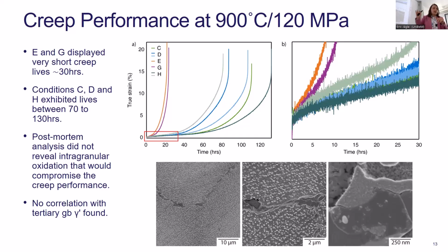So condition C here looks okay, but it doesn't stick out. So the gamma prime distribution didn't seem to influence necessarily the creep performance. So just the finer gamma prime seems to be equivalent to the larger gamma prime as well. Condition C, D, and H, so the blue and green lines in there, all are about the same.